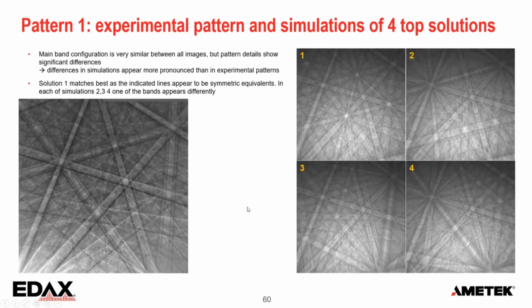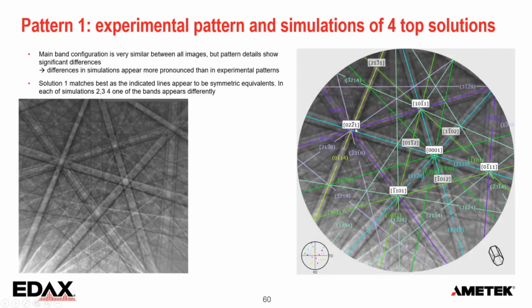And those are the ones that were really stronger in the experimental patterns compared to those. So now these are the top four. Then I just say, okay, let's take a look. And in this case, I'm looking at those three bands. And if I go back here, these bands appear the same. And here, this one seems to have a number of higher order reflections. Here it's at the top, here it's at the right of the triangle, and here it's at the left of the triangle. So this yellow line indicates an asymmetry. So it's not the same. Just to illustrate that, you can ignore the rest of the pattern in this case. You can see that, and then we can index it because we know that those three have to be the same. So then we can get a reliable indexing confirmation.